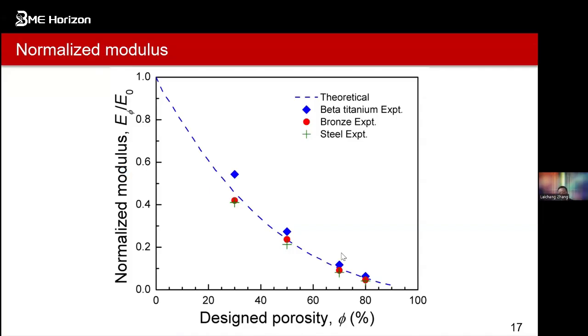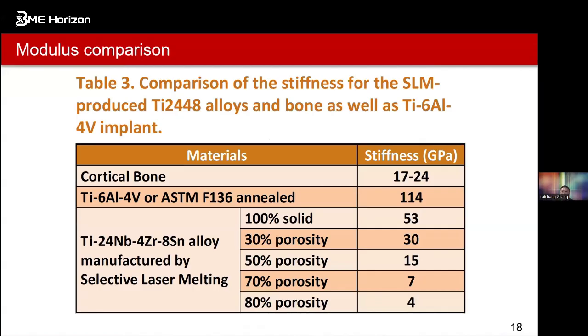This is the curve from the data theory. But when we see the data, we use the scaffolds. You can see scattered data for the structures for the titanium, bronze. You can see just very close to the structure itself. So of course, you can see, coming back to the Ti2448, you can see this one is Young's modulus we can control very well.